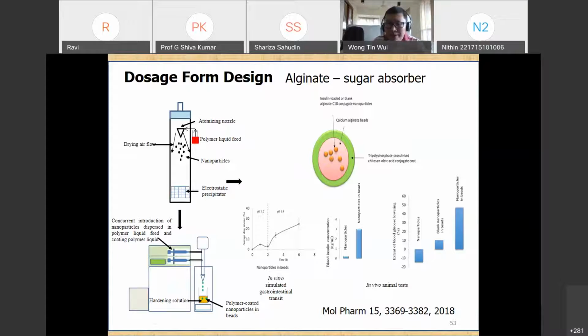Looking at the in vitro drug release data, however, we found something unexpected. Our coated bead structures are able to reduce the early release in the gastric regions. However, in the intestinal regions, only about 30% of the insulin is released. Nonetheless, a high bioavailability of insulin is observed in the in vivo study. The main reason is that the insulin is delivered into the systemic circulation not just by free insulin absorption transmucosally; the insulin is also absorbed by penetrating through the intestinal mucosa and entering the bloodstream thereafter.